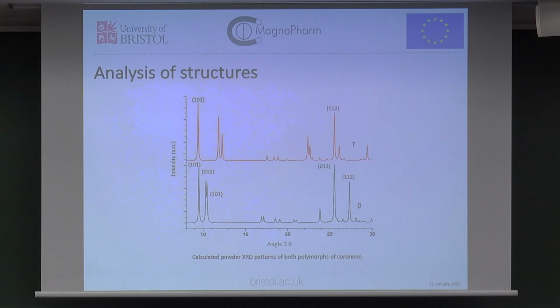Of the two structures, this is the powder diffraction patterns. The reason I've indexed these particular peaks is that they're going to be relevant in a minute. If you were to overlay those two patterns, the 101 bar and the 012 peaks of the beta pattern at the bottom would be basically underneath the 101 bar and the 112 reflections of the gamma coronene. So if we were to mix those two patterns, it would be the 002, 101 and the 112 peaks that we would see emerge.